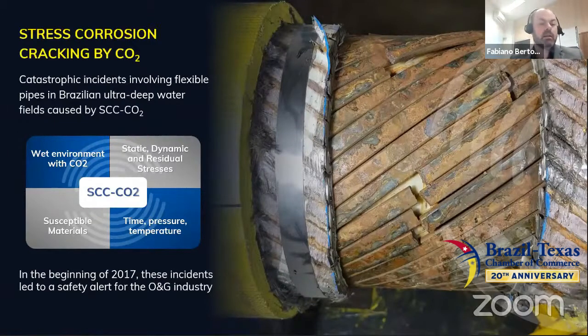Okay, thank you. Let's talk about the main subject of this presentation, SCC CO2. It means stress corrosion cracking by CO2, a failure mechanism well known by the industry. However, the SCC CO2 was not fully mapped by the flexible pipe industry as a critical risk until the recent application in production fields with high CO2. One evidence was the accidents in the Brazilian ultra-deep water fields at the end of 2016 and the beginning of 2017 that led the Brazilian National Petroleum Agency, ANP, to issue a safety alert for the industry.